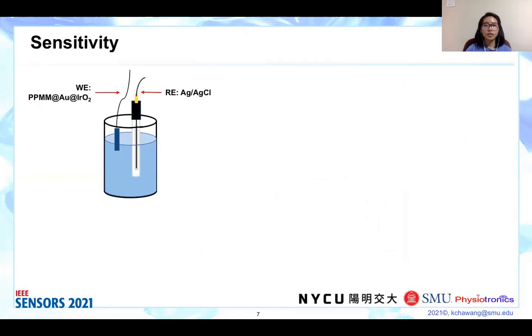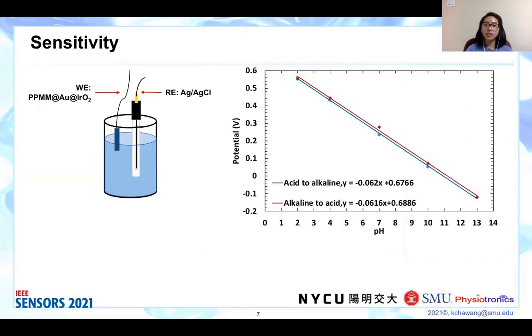The potential difference between the working electrode and reference electrode is recorded using a LabVIEW-based program with a sampling rate of 7 samples per second. Sensitivity is investigated for 2 test sequences, acid to alkaline, which follows the path pH 2, 4, 7, 10 to 13, and alkaline to acid, which follows the path pH 13, 10, 7, 4 to pH 2.